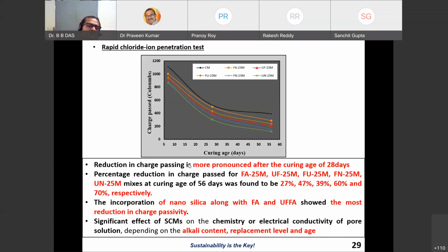Next is your rapid chloride penetration test. Well, here you can see all of our mixes except the control mortar. The control mortar at the early age, 3 days, was more than 1,000, but the moment the age prolonged, the design mix was only for mortar, so the porosity will definitely be much less. So the charge passed kept on reducing, but you can see the green line is showing the lowest. Green line showing the lowest.